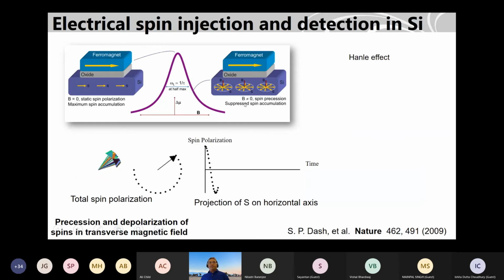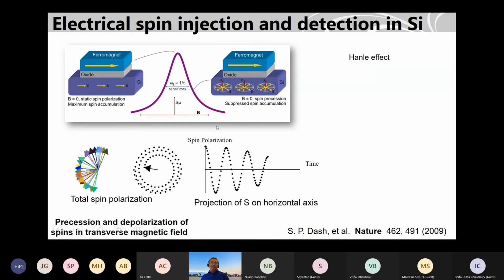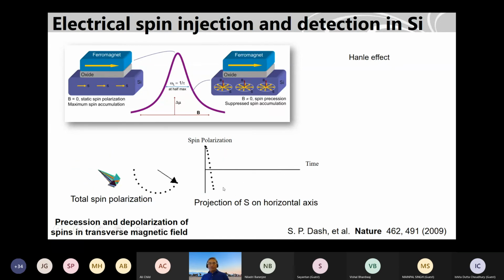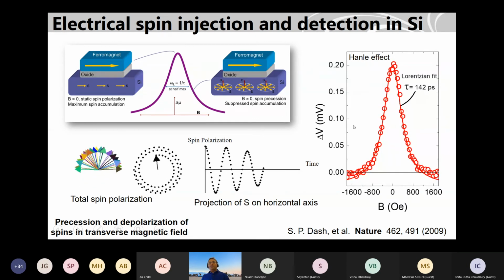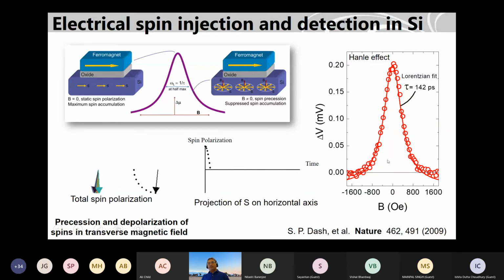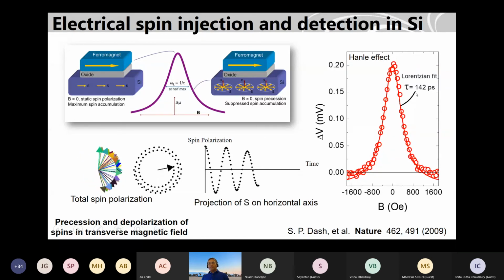When you apply this magnetic field, spin should precess, and you should get no spin polarization at some point. If you do a time resolved experiment, you should be able to see this, but we don't do a time resolved experiment because optical experiments are challenging in silicon, as it's an indirect band gap. But when we do this electrical measurement, we see such a Hanle effect. From the line width of this signal, we can find the spin lifetime. And this is all at room temperature. It's around 150 picoseconds.